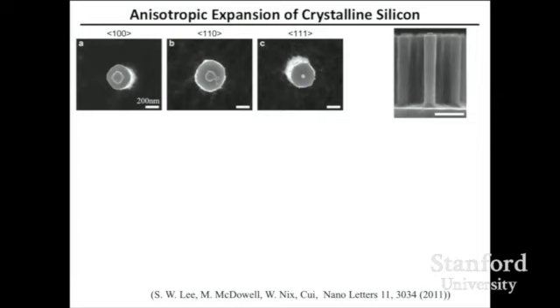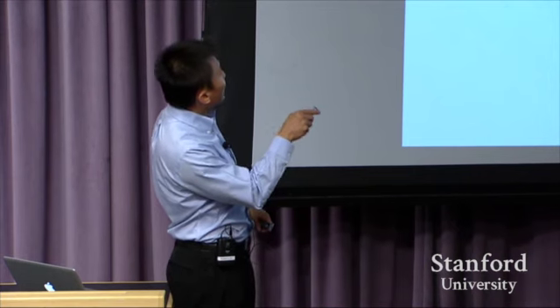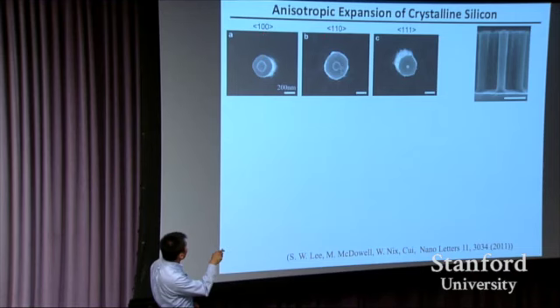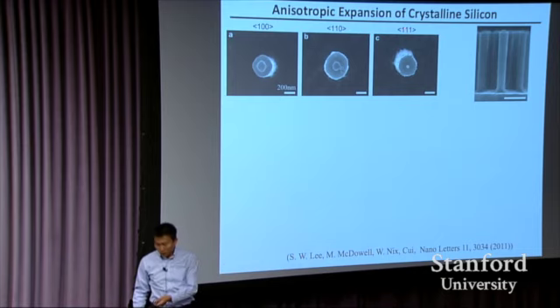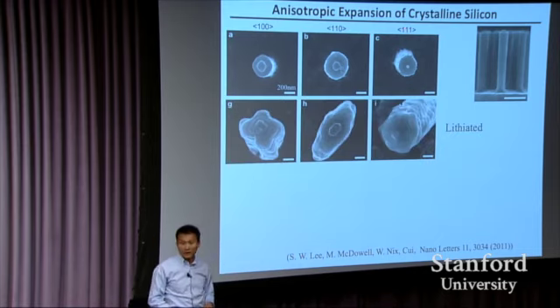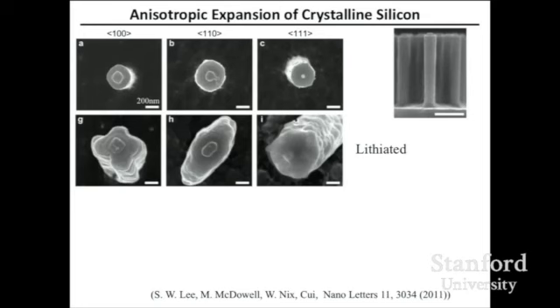Through several years of research, working together with a number of very talented graduate students and postdocs, and with different expertise and different research groups, we figured out problems one by one. For example, if you ask the question, how does silicon expand? Do they go like this, isotropically, or is there something very different going on? So we patterned this pillar with a round shape along the 1, 0, 0, 1, 1, 0, and 1, 1, 1 directions. As soon as you put lithium in, you see something dramatic happening. The 1, 0, 0 becomes a cross shape, the 1, 1, 0 becomes an ellipse shape, and the 1, 1, 1 becomes round, or more or less a hexagon shape.